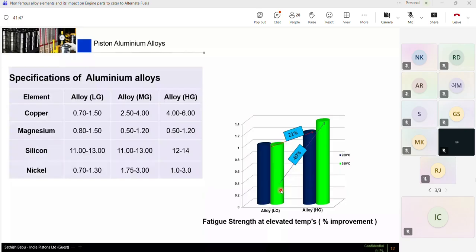we tried to manage with the upcoming emission norms, but the upcoming emission norms started asking for a lot of reduction in their parameters with respect to PM and NOx. So all these things have influence with respect to the piston material. The piston material like silicon and copper plays a major role. And when the power density increases in the engine, to meet those tighter emission norms, when the cylinder pressure and heat release rate started increasing, we went to this medium grade alloy, which asked for a copper percentage of 2.5 to 4 and a higher nickel content. So we saw a good improvement in wear resistance and also a good improvement in fatigue strength.